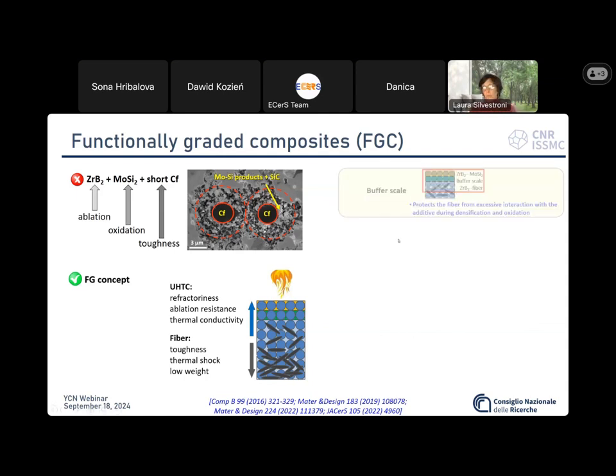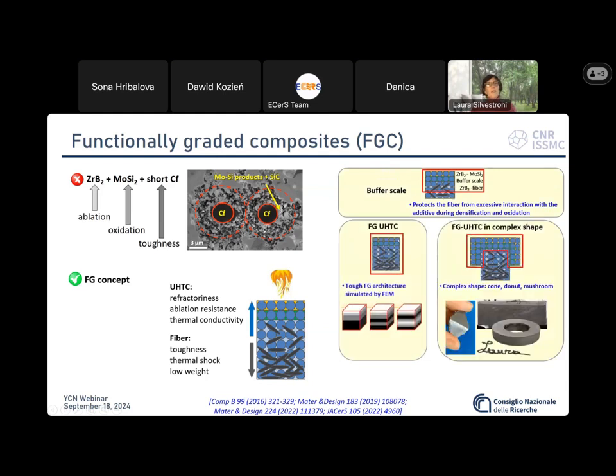But, of course, we have to take care of prevention of fiber deterioration upon excessive interaction with the additive. So we need to actually find the right one, and we can actually change the sintering additive across the thickness of the composite. Then we have to couple layers of different composition and thickness that can induce cracking instead of increasing toughness. And this is also something that must be considered.